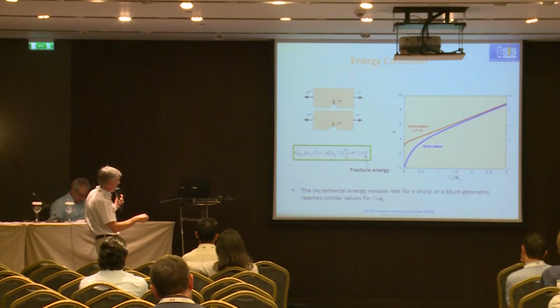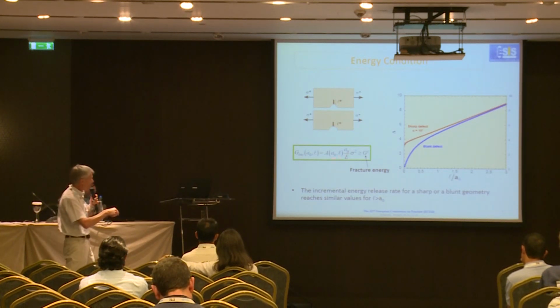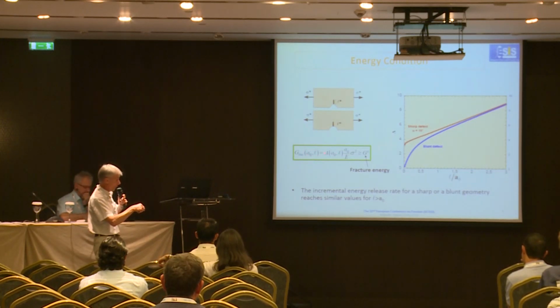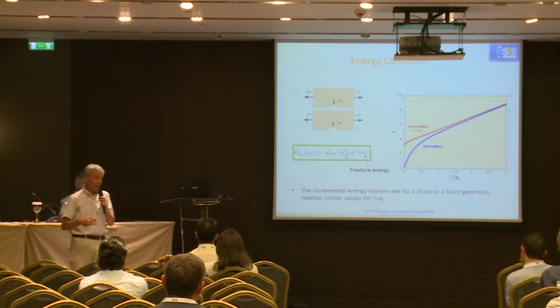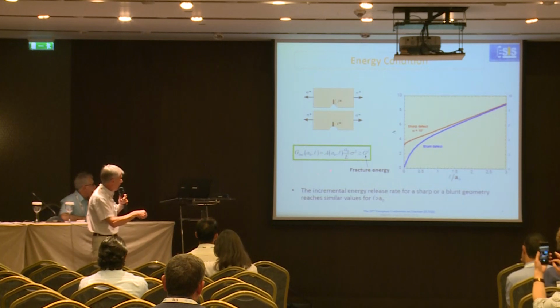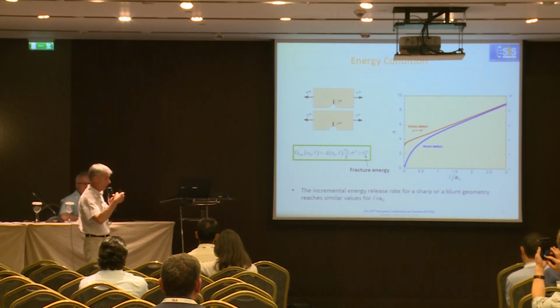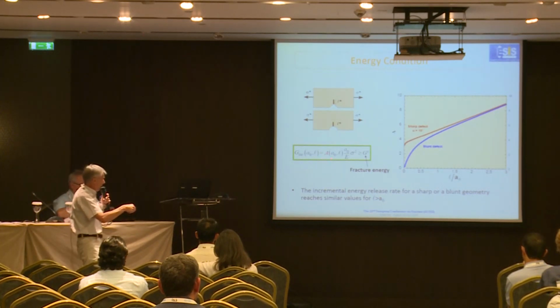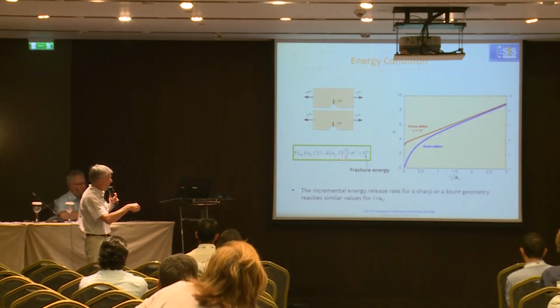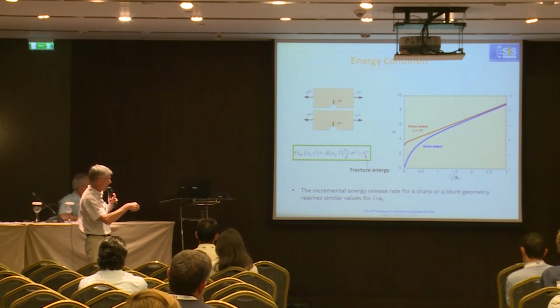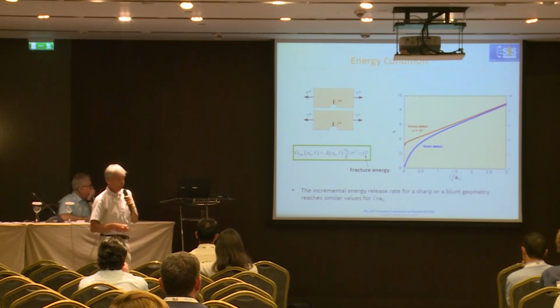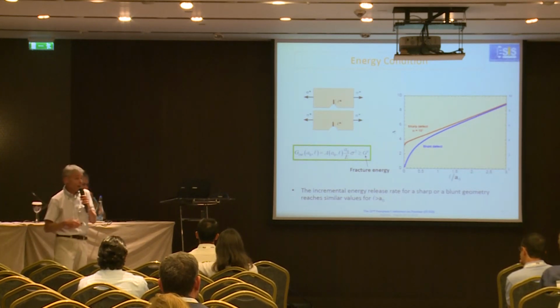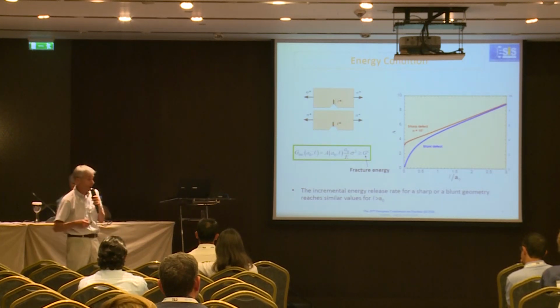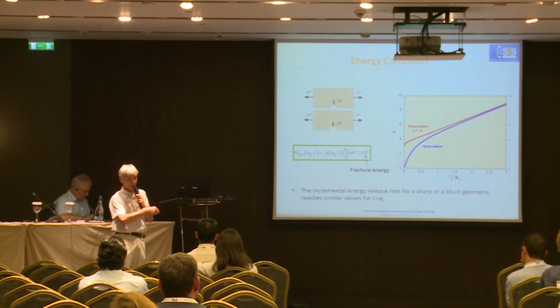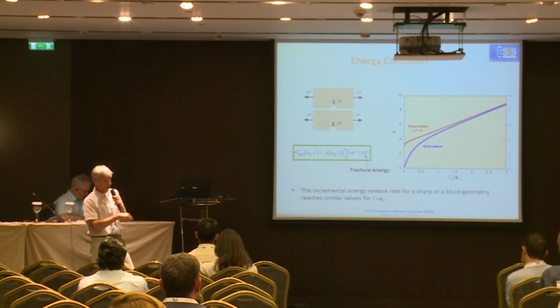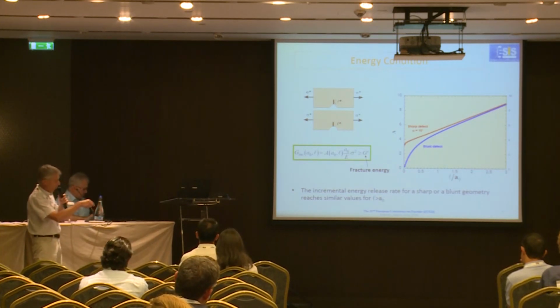I'll start with the energy condition, which is written here. We define the incremental energy release rate, which is similar to the classical energy release rate of Griffith, except that the differential increment is replaced by a finite amount of crack increment. The incremental energy release rate must exceed, at crack nucleation, the fracture energy GC. Here we have a scaling coefficient, which is easy to obtain with standard finite element tools. You perform an elastic calculation and obtain this scaling coefficient, which is plotted here versus the crack length. You can see it is an increasing function.